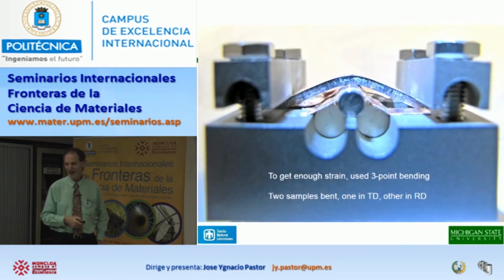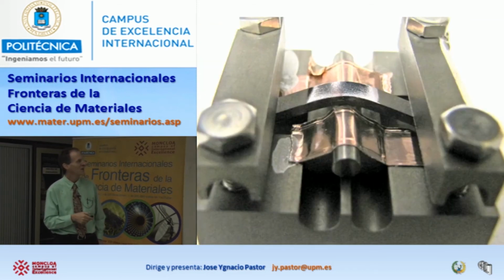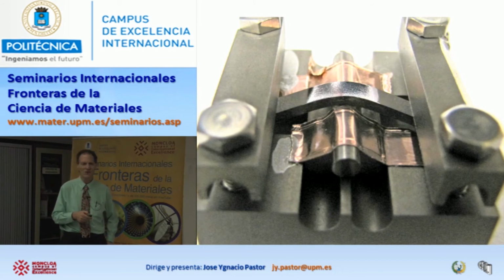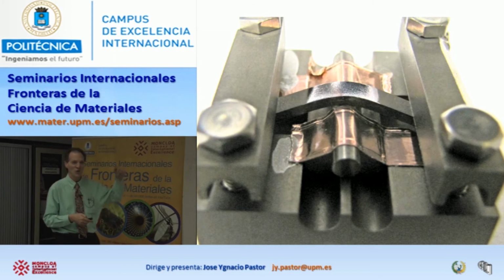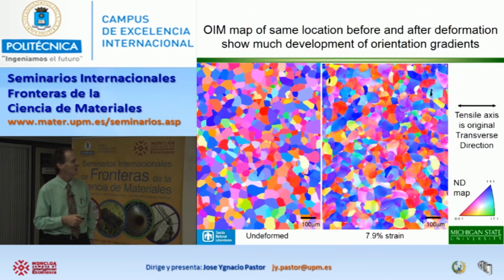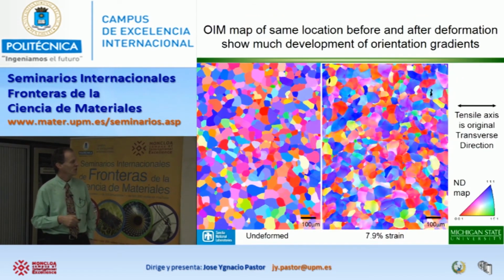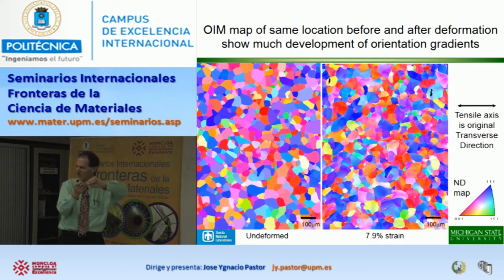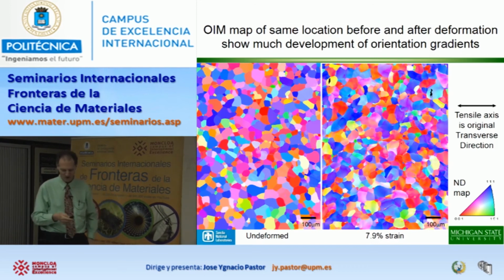Then we took this tantalum polycrystal and we bent it and looked at what was going on right there where the strain is high. Here you can see this orange peel effect, the differing amounts of strain in different grains leading to surface roughness. And here is the original microstructure. Here it is after it is deformed. And you can see that there are gradations in color, which represent gradations in crystal orientation. The grains are twisted and bent as a result of the dislocation behavior.